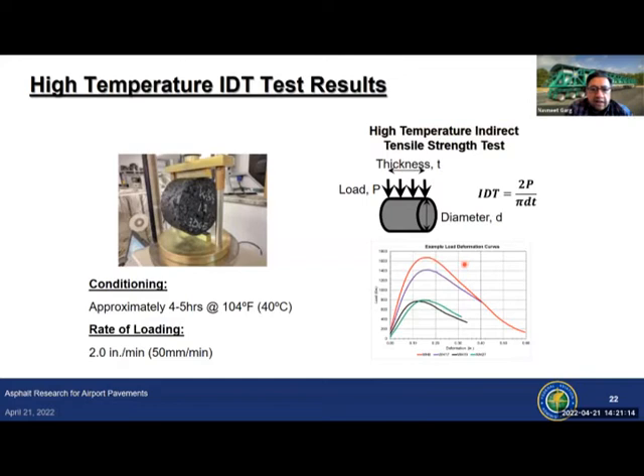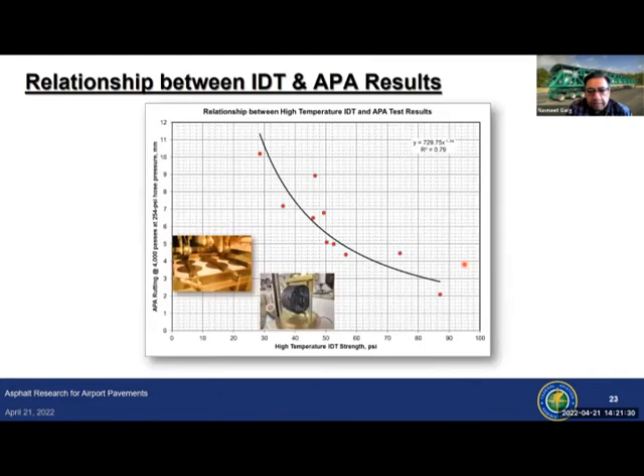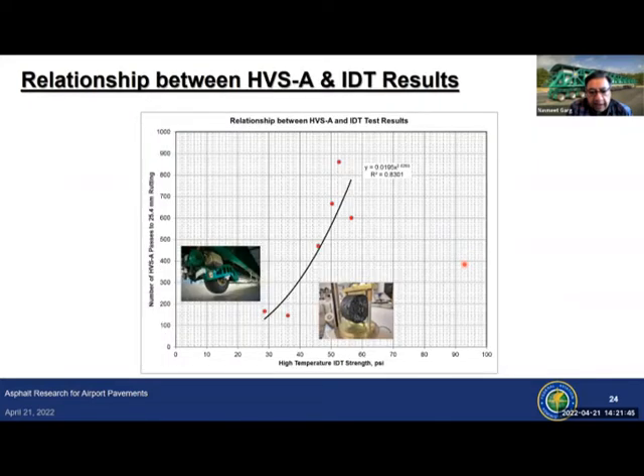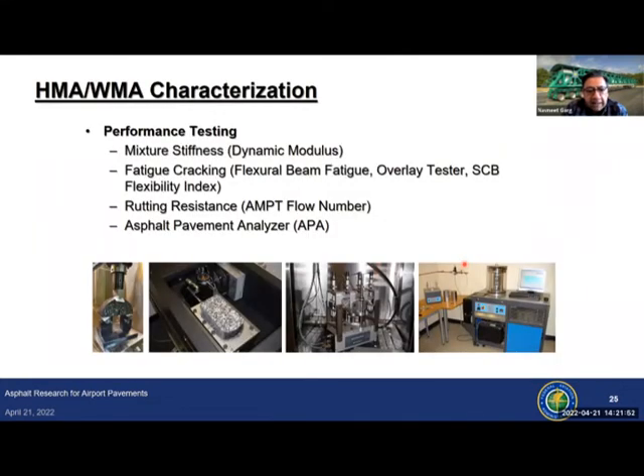Another test we looked at, and are also currently looking at, is the high temperature IDT test. It's a much simpler test to perform. You can perform this test using a Marshall press, which most of the labs have, and it can even be used during production time to make changes to your mix. And what you see in this chart is the data from APA rutting and high temperature IDT. Since both tests relate to rutting, there is a very high degree of correlation between the test results. And here you see HVS rutting compared with high temperature IDT. And there are other tests that we perform: 4-point bending beam fatigue tests, dynamic modulus tests, flow number tests.